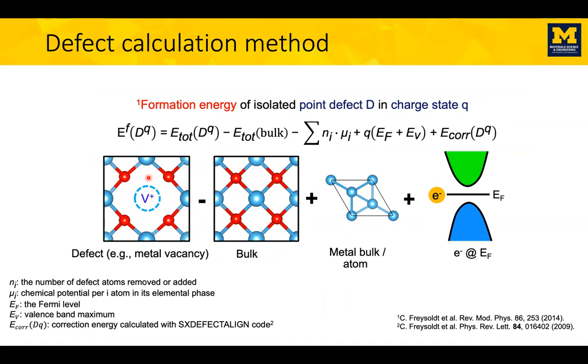The way we calculate this, we make a simulation cell where, for the case of a vacancy, we remove one of the atoms and we make a comparison between the defective cell and the pristine cell. And we look at the energy difference. But we're not done yet, because we removed an atom. What did we do with this atom? Did we put it in a low energy state or a high energy state? So we need a reference state.